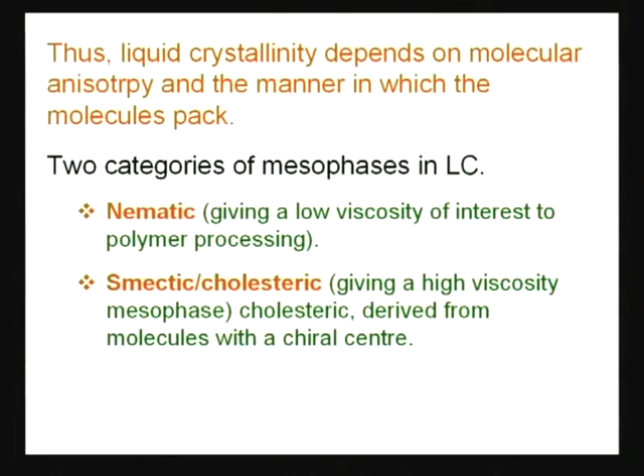By virtue of such configuration, we can get two categories of mesophasic structures in liquid crystalline materials in the liquid phase. One is nematic and the other is smectic or cholesteric. Nematic is characteristic of a material of lower viscosity, which is of interest in polymer processing, whereas smectic shows high viscosity either in solution or in melt condition. So, two major categories of liquid crystalline polymers are nematic phases, or smectic or cholesteric phases: nematic LCs, smectic LCs or cholesteric LCs.